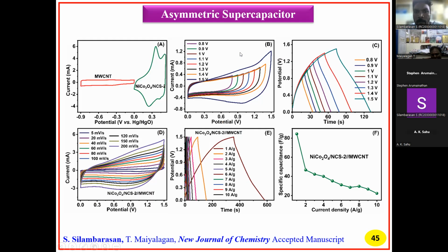So next, figure B: here, with the same scan rate but a different potential, we measured CV in the two-electrode system. Figure C is for the same current density but a different potential, measured as charge discharge. Figure D is for different scan rates from 5 to 200 millivolt per second, with a potential of 0 to 1.5 applied, and current densities from 1 ampere to 10 ampere per gram measured.